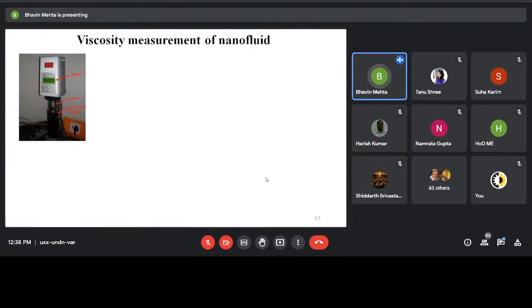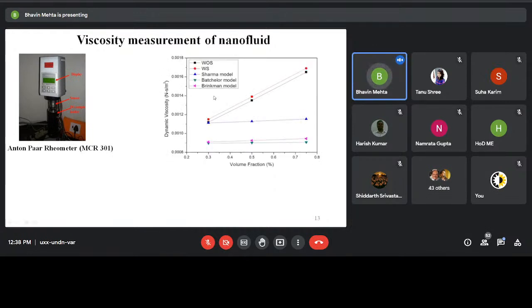The viscosity of the nanofluid is measured with the Anton Paar rheometer, which is available at the institute. And we found that there is a drastic rise in the viscosity also. But the results deviated from the suggested models for higher volume fractions. But for lower volume fractions, the results suggested by the Sharma model were quite in agreement with the actual results.